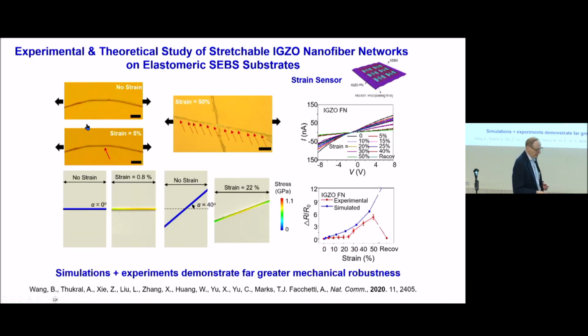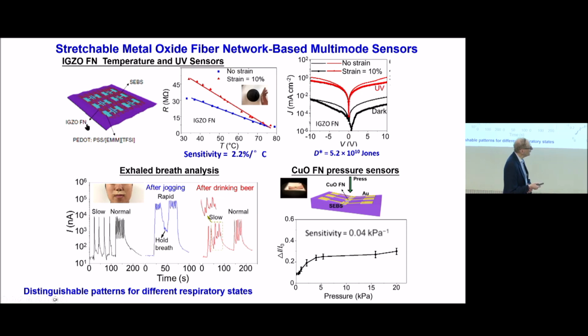And you can show that, again, because imagine the Brillo pad is the extreme, but you can stretch it a lot. You stretch basically the network of fibers, and you can show quite good mechanical properties, and you can make a strain sensor. And some of this work was done by people who do finite element analysis to try to model how the strain is dissipated. But Binghao said, oh, I'm going to make devices. So here's a strain sensor using and FN means fiber network. And here's a strain sensor.